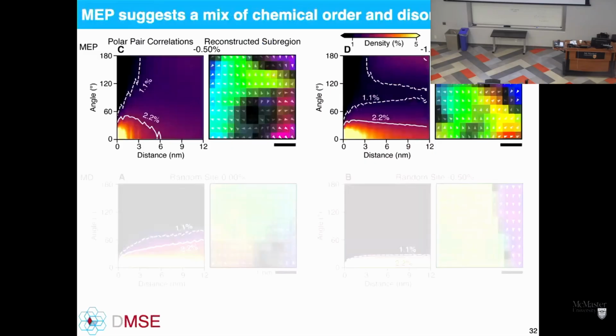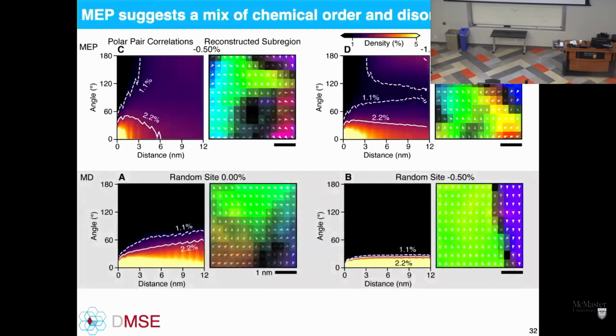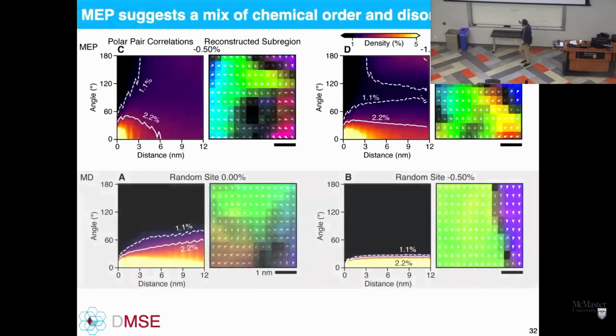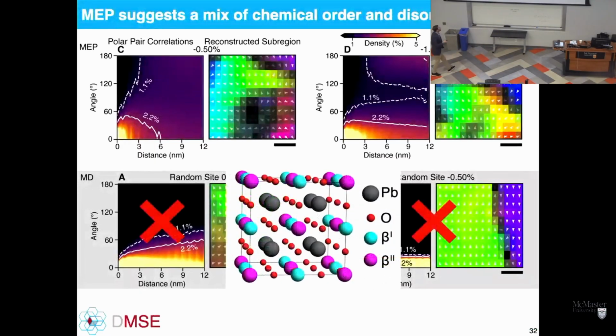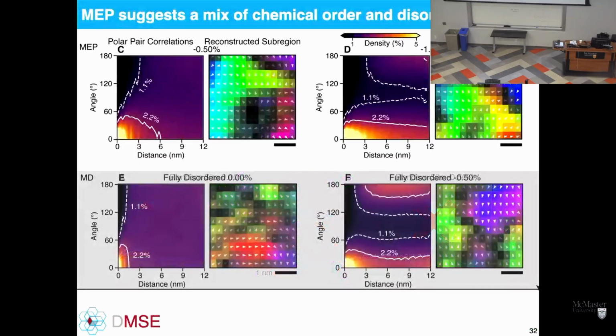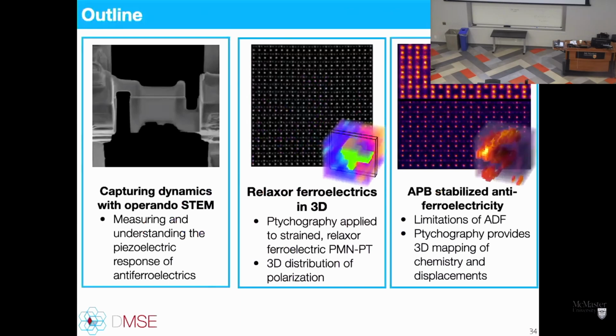Oh, and the other thing, as I mentioned, these cases have these head-to-head domain walls. This never occurred in the random site model, but when we added chemical disorder to that, there you start to end up with these head-to-head domain boundaries again. This would not have occurred otherwise in the models without including that composition.